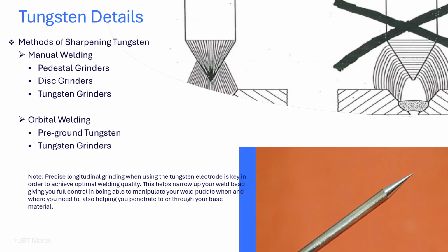Another thing you can see here, this is not your ideal way to sharpen a tungsten. When doing it on a tungsten grinder, you might see somebody turning the tungsten sideways as the wheel's spinning this way. That'll get you this result, which is not ideal. You can use it. I'm not going to say that you can't make a decent weld sharpening a tungsten that way. You're just going to have a lot better results if you do it longitudinally like this in a straight down direction. That allows you to have a more precise punch power through the material to get your penetration that you wanted and not having all of that energy being dispersed over a wider section, which allows for wider weldments, which allows for more deviations in the weldment. So as long as you can keep things narrow, tight, and small, that usually keeps everybody pretty happy.